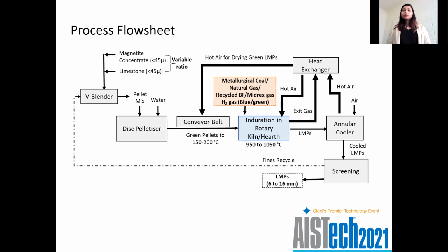when they are being transported. Then during the induration, we have considered two separate processes, one with rotary kiln, one with rotary hearth for the cost analysis. And then the pellets are cooled down in an annular cooler. The off gases, the sensible heat of the pellets are being utilized to preheat the air that can be used in the heating stages. And then the cool pellets are screened, and the fines are then recycled back. There will be a crushing stage involved somewhere in this part.